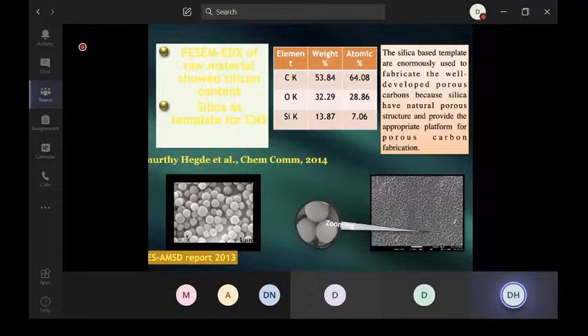So here we found the literature, because silica is 13%, which is very high. And there is a similar report published in 2013. We have not worked on a similar kind of material, but he worked on some other materials. But he also used the template approach, and we also follow the template approach. Before making the nanoparticle, silica is porous in structure and silica is present in lignin. I already told you lignin percentage in this kind of material is nearly 30%. That is huge. In 30%, 14% is silica. So we all know that silica is porous in nature. So silica created the porous template there.